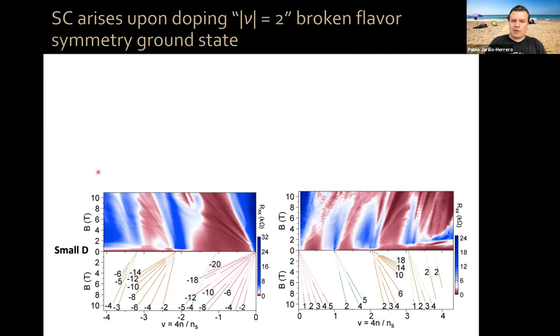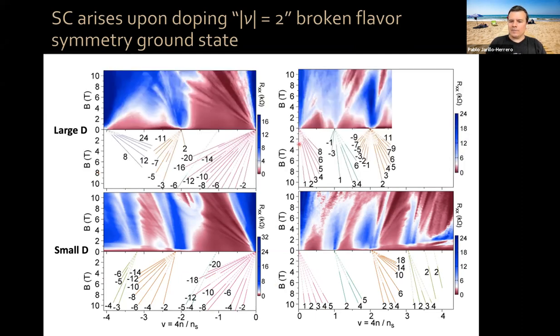Now, if we go to high displacement field, however, then we see that the Shubnikov-de Haas oscillations have some fan diagrams pointing away from charge neutrality, but you have others pointing towards charge neutrality. If you point away from charge neutrality, for electrons, it means extra electrons. For holes, it means extra holes. But if you point towards charge neutrality, on the positive filling factor side, it means you have hole-like Fermi surfaces, and here electron-like Fermi surfaces.